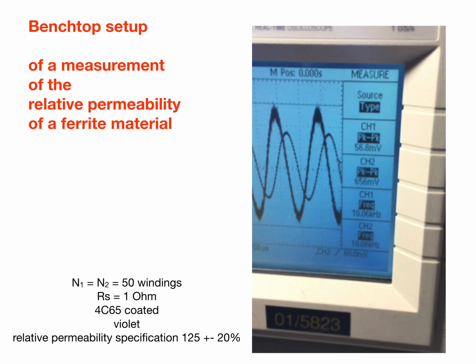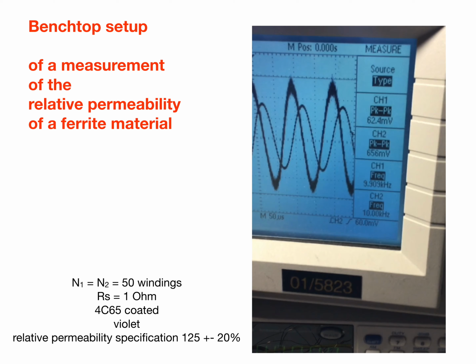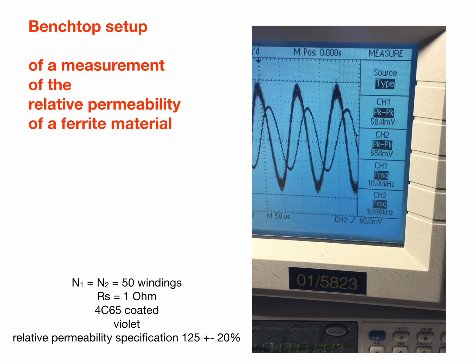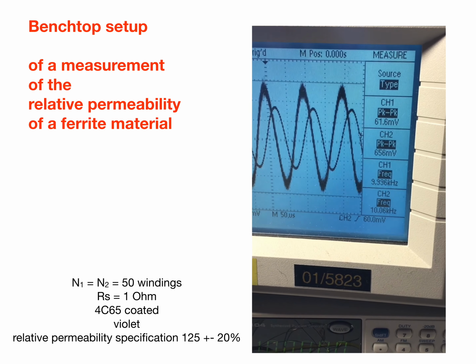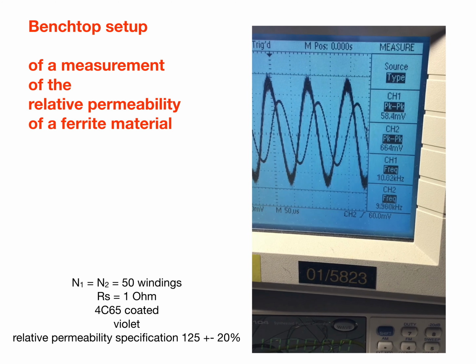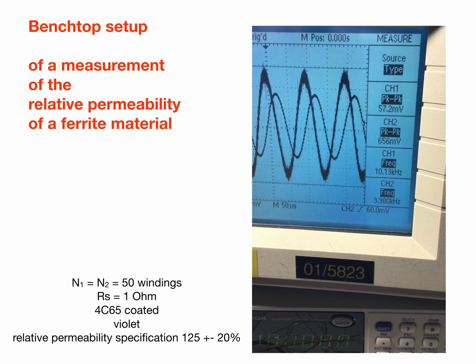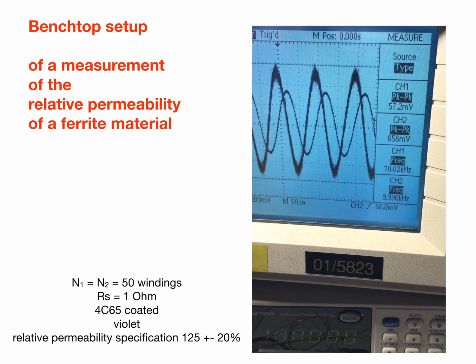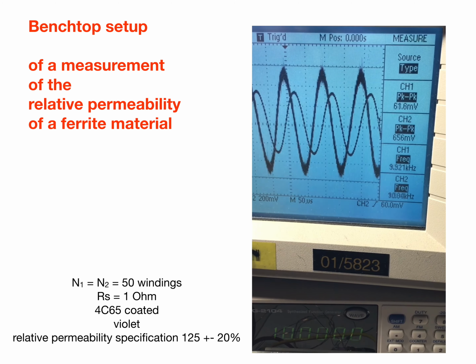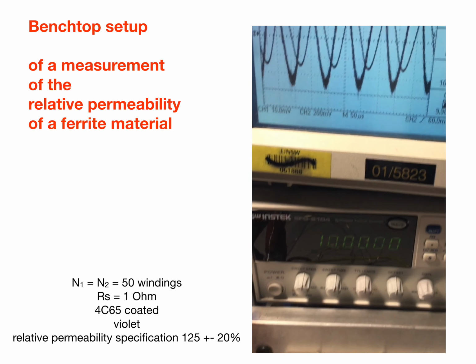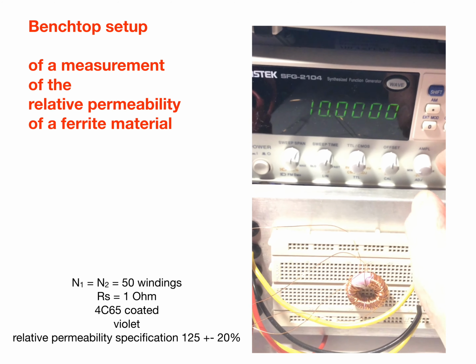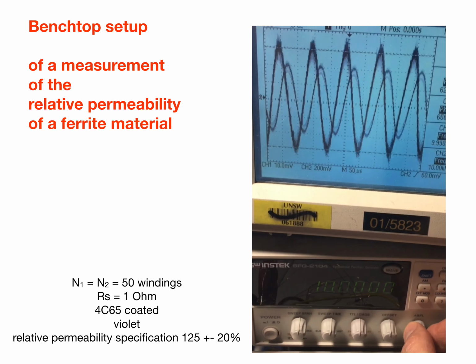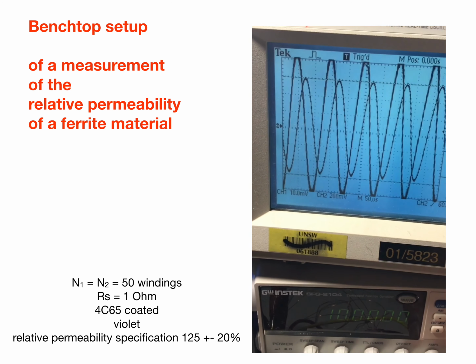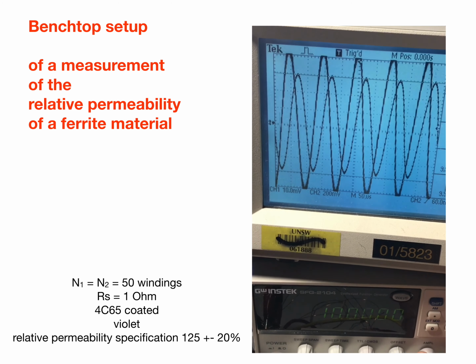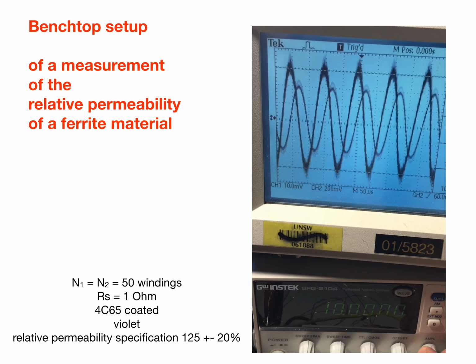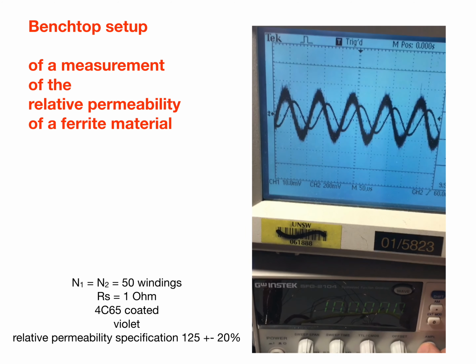Using the measurement option of the oscilloscope, the peak-to-peak results for those voltages can be measured. At the moment, channel 1 has a peak-to-peak of 56.8 millivolts, whereas channel 2 shows 656 millivolts. The frequency is 10 kilohertz. By changing the amplitude, one can vary the voltage outputs of both coils, and it's apparent that the voltages are proportional to each other.